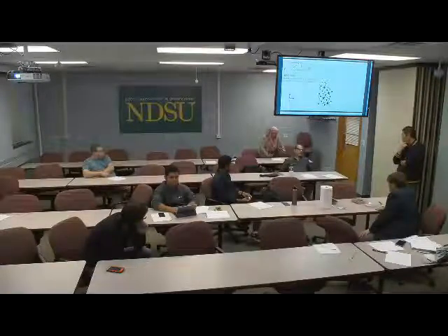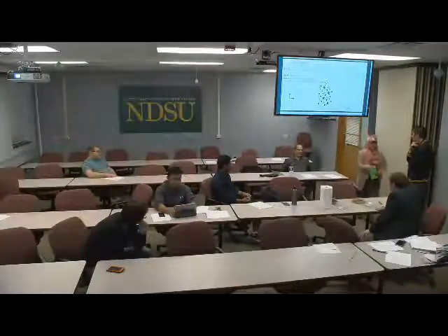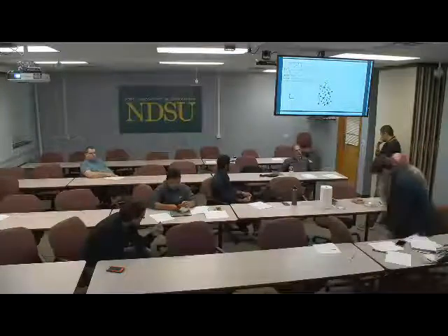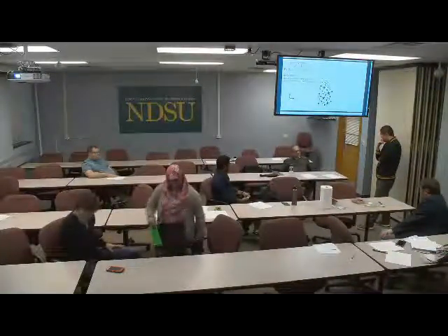We just use the Redhead equation, so you just put in the peak temperature into the Redhead equation, and then you get a binding energy. So that is in the first paper, I think. Right. In the supplemental, I think it's explained how to do that. Yes. So you can just get the binding energies in that fashion from the TDS. But nobody knows what the prefactor is, right? Depending on what prefactor you put in there, you can get any number. Right?